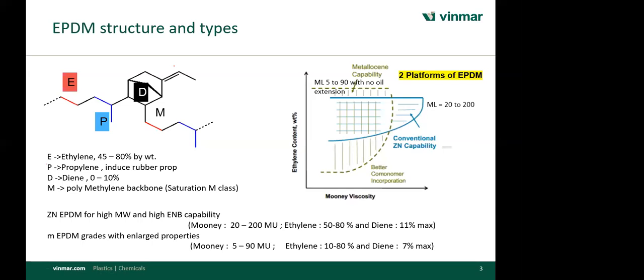Each technology has its own advantages and disadvantages. With Ziegler-Natta technology, we can produce EPDM from Mooney 20 to 200 and diene maximum 11%. Whereas in metallocene technology, we can go Mooney as low as 5, but the maximum achievable Mooney is 90, and diene is maximum 7%. In metallocene we also have the advantage of producing low ethylene content, as low as 10%. If somebody is looking for a grade with a lot of flexibility, flexibility comes from the propylene segment. So 90% propylene EPDM can only be produced through metallocene technology.